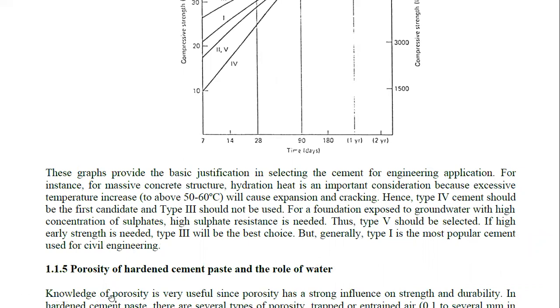and for groundwater foundation exposure, type 3 cement, sorry, for sulfate resistance type 5 cement is selected. And where excessive temperature increase is a concern, we are not using the type 3 cement, but type 4 cement should be used.